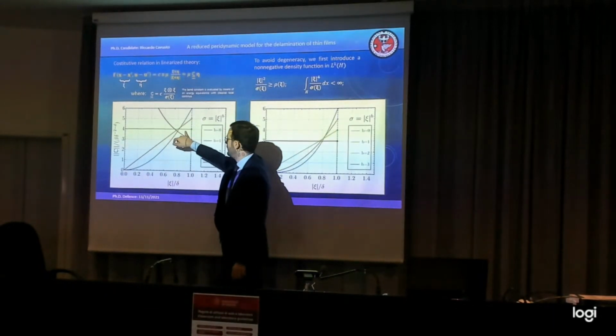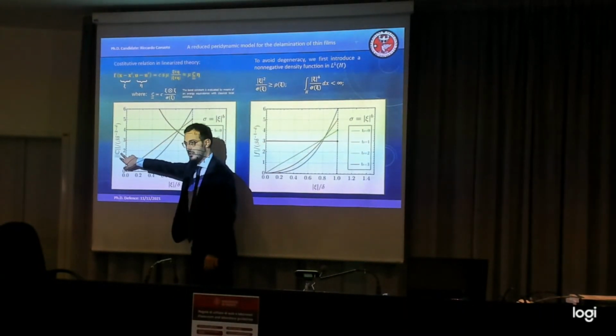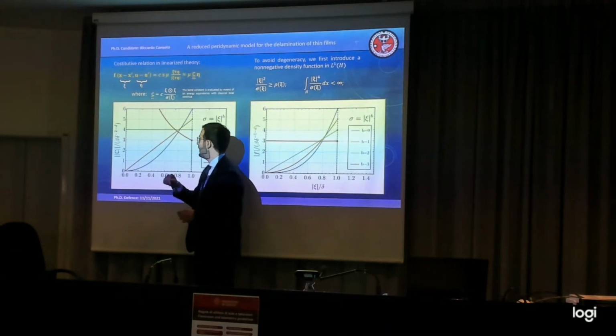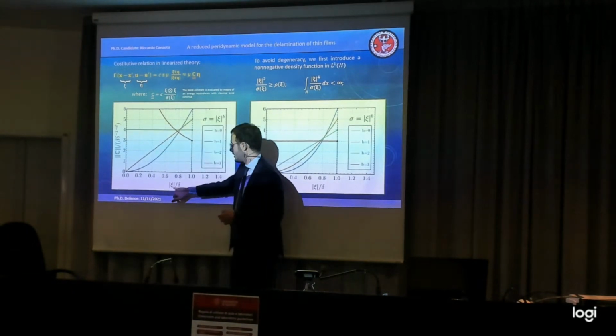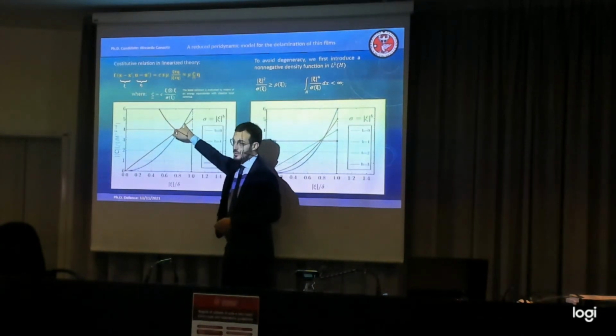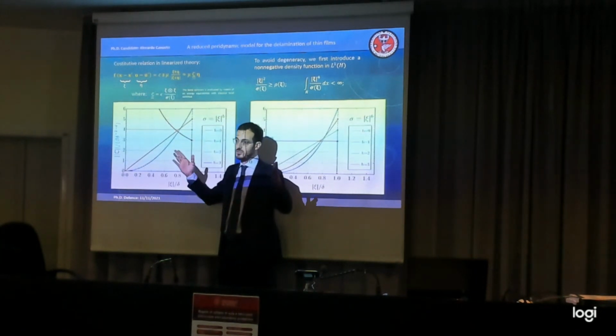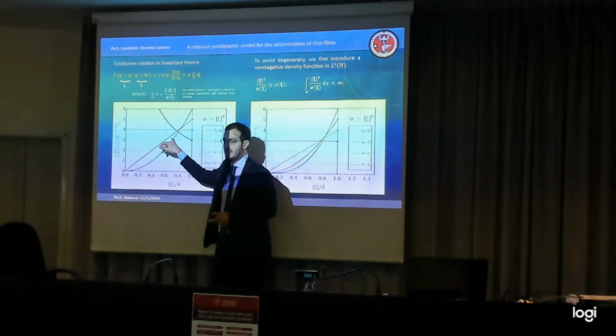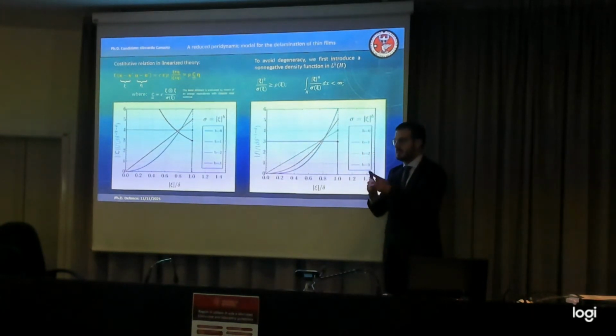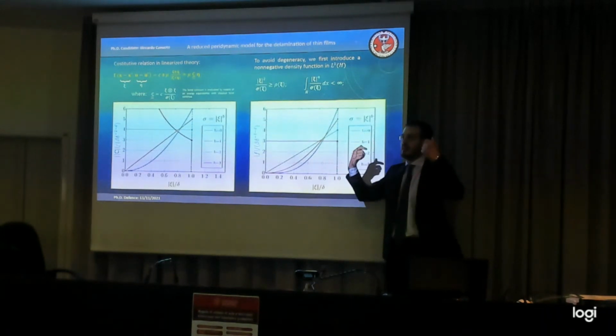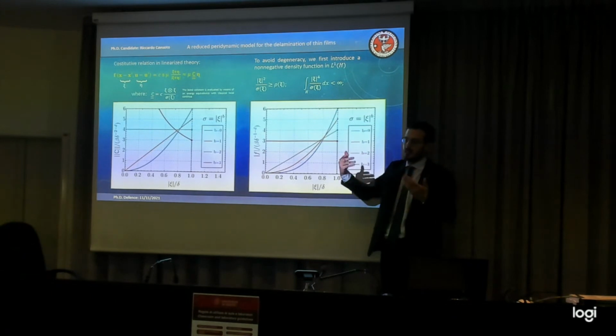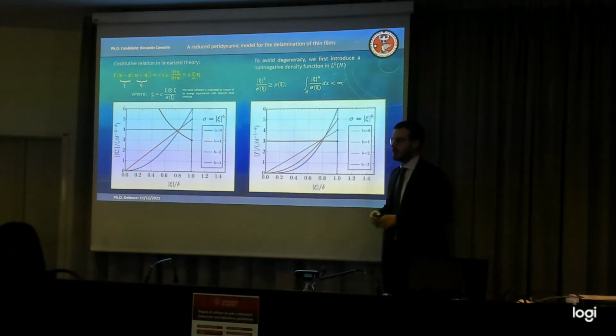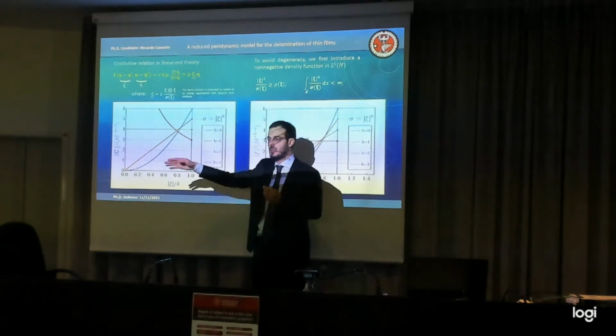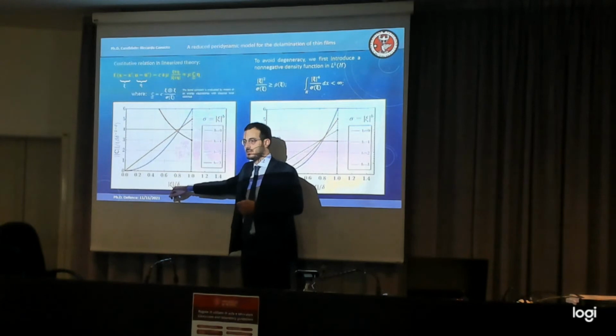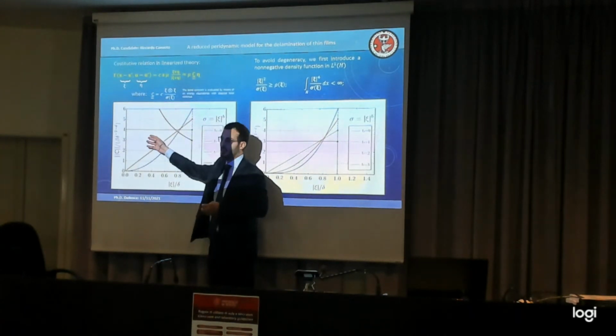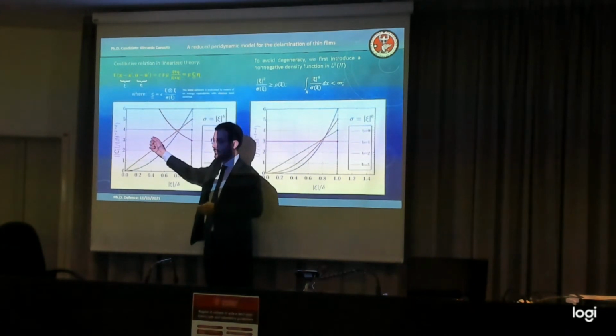So this is a kernel in which the stiffness that two points are exerting onto one another is constant when the bonds are more far apart. But then there are also other models in which the stiffness can grow as the particles are more far apart, and in these cases you end up having a numerical discretization that has bonds that are far apart, which also have higher area, and so the stiffness is not reduced but is increased. So the way that the stiffness goes by increasing the distance between two points is just an assumption that you made at a local level on the kernel of the local integral.